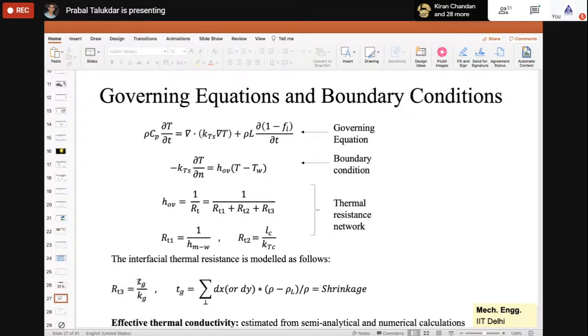Now this air gap, Saurav was able to calculate by using a simple mass balance, right? He was able to calculate the shrinkage, or this gap which is formed because of the shrinkage of the solid material. He does a simple mass balance, and from the density difference, he was able to calculate this Tg from the model, right? So he used these relations from the mass balance, and every iteration he calculates what air gap forms because of the contraction of the liquidified metal, right? So that Tg is known to us from the simulation.